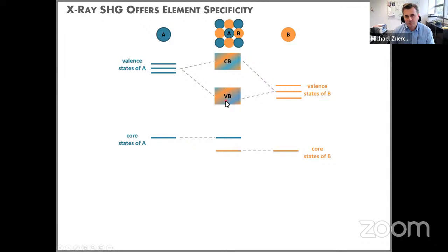The one thing is that we form bands as we go from individual atoms to, say, a crystal. So we form continuous bands in the valence states. The other thing we know is that we hybridize. There is a mixing happening between the wave functions of A and B, resulting in mixed-state valence and conduction bands. That's what we typically refer to as hybridization. On the other hand, the core states are typically so energetically separate that they don't hybridize. They are not typically mixing. They stay separate if we bring this together, merge it in a combined system.